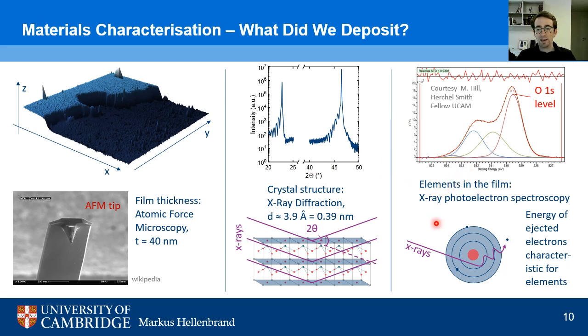A second approach, also relying on X-rays, is that we shoot X-rays with much higher energy into our sample, and this high energy now can kick out electrons from individual atoms, and by measuring the energy that these electrons have after being kicked out, we can calculate what kind of atoms we have inside the crystal structure. So remember again that depending on the element, as I explained before, electrons will be bound to the nucleus with different strengths. And thus, by measuring the difference between the incident X-ray energy and the outgoing electron energy, we can calculate how strongly the electrons were bound to the nucleus, and thus which atoms we have.